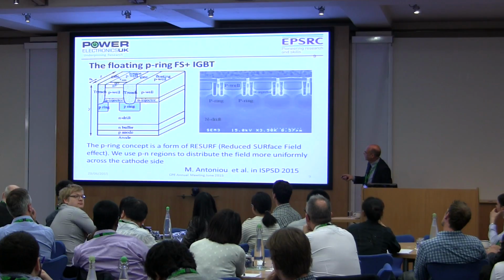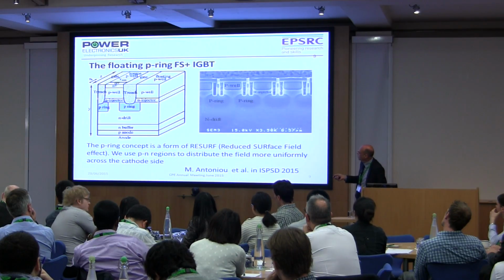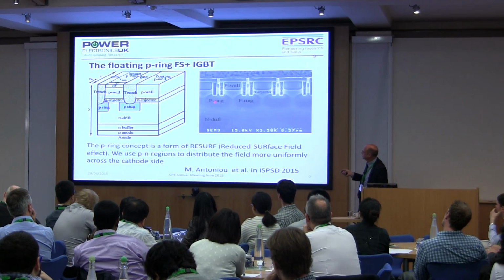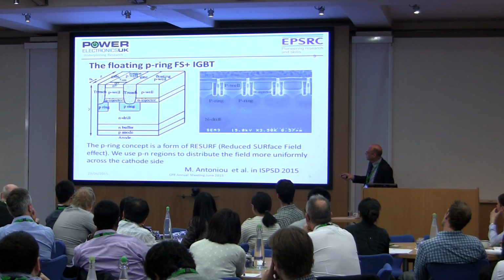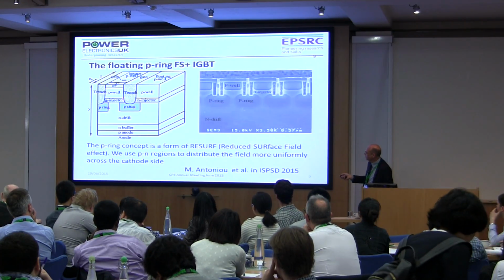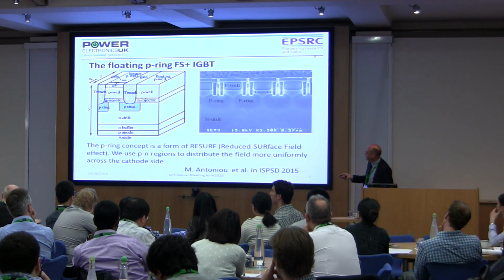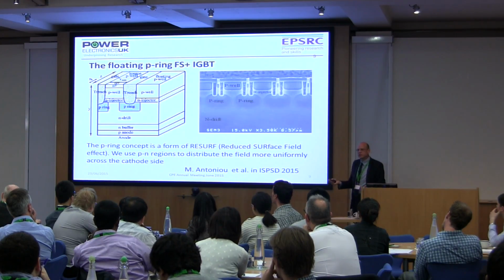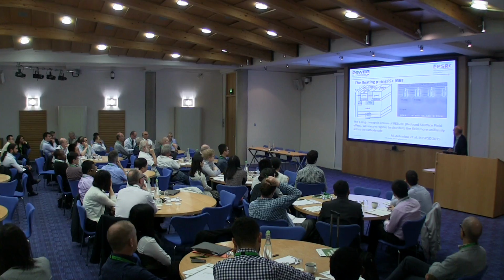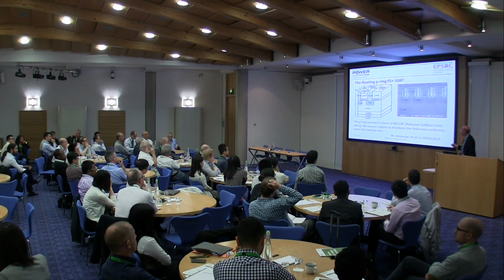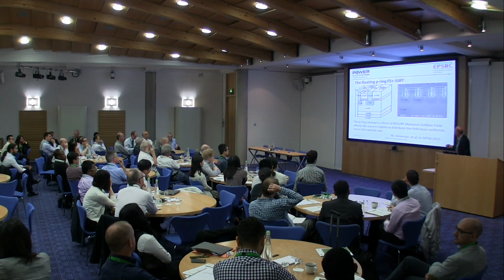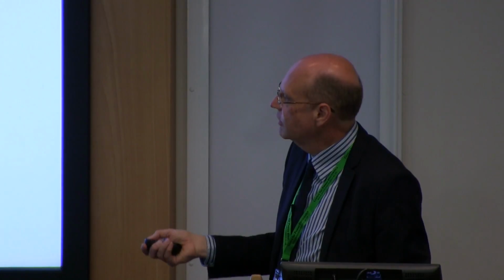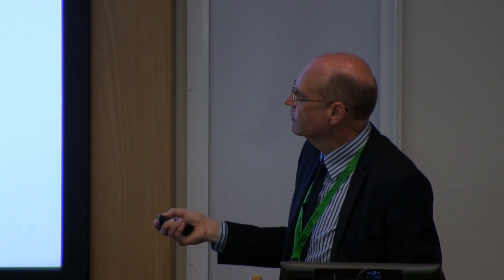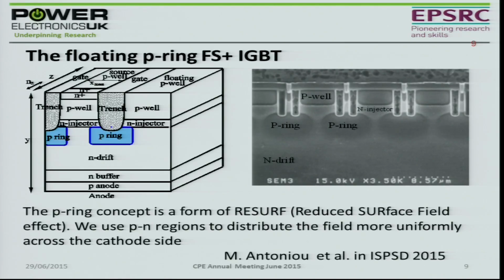What's often a problem is how you make this injection across the surface as uniform as possible. If it's only being injected from one point at the edge of the end of the channel here, then that will cause the resistance to be higher than it need be. So by spreading it out using this injector, it gives you a much lower on-state resistance, causes the injection to be from both sides, very high injection from the top and the bottom. So it gives you the lowest on resistance.